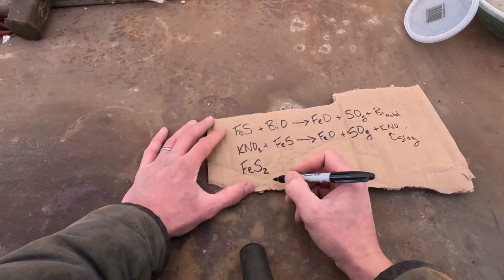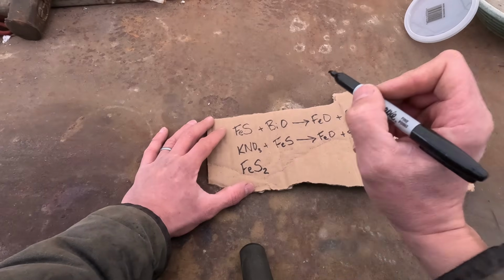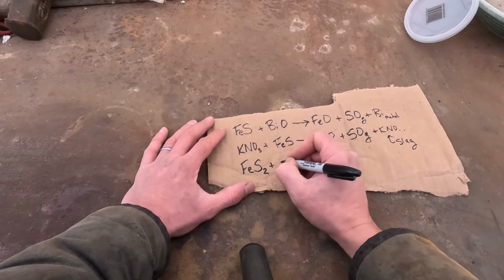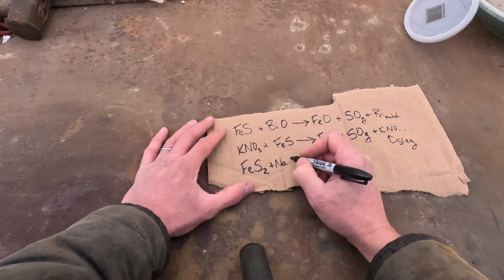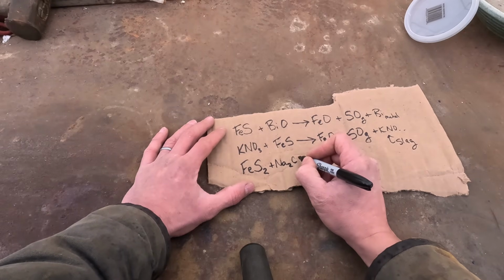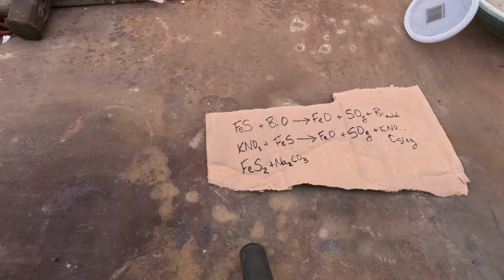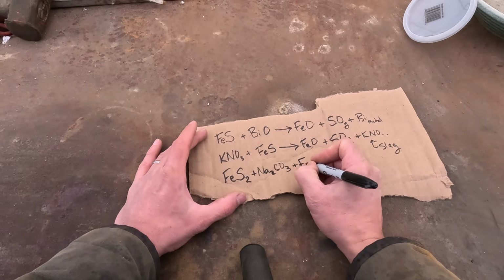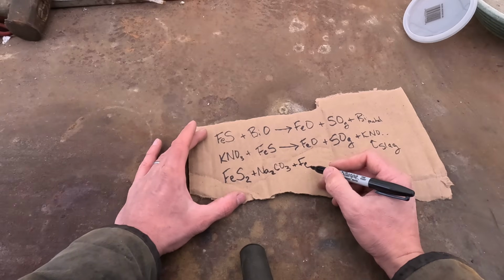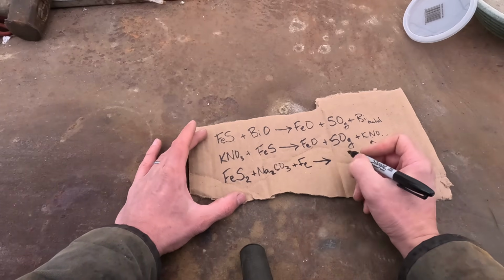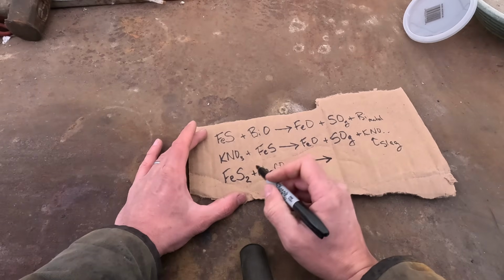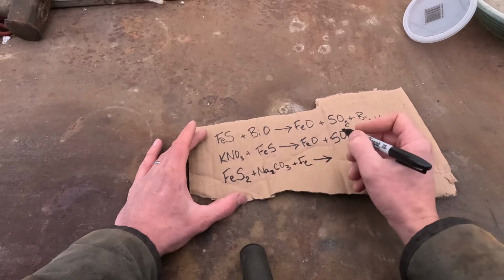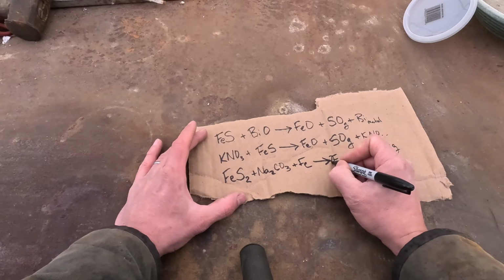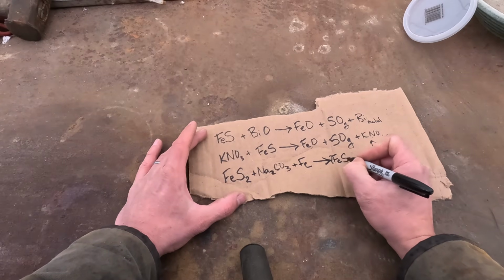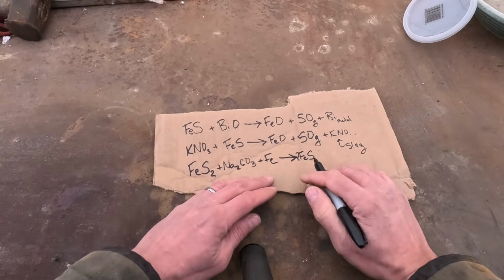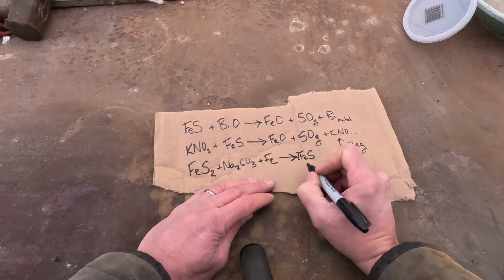It is not soluble in the slag. This will not be absorbed, it will form a matte layer. But if you use enough soda ash, oh boy, sodium carbonate, Na2CO3, hold on, let me look that up. And you add in iron as nails, what happens is you have the iron react with the iron sulfide to convert it to FeS. This is a different form of iron sulfide, which is absorbed by our slag.